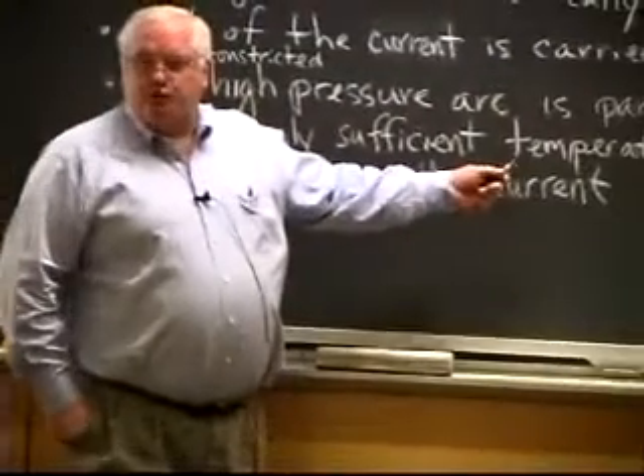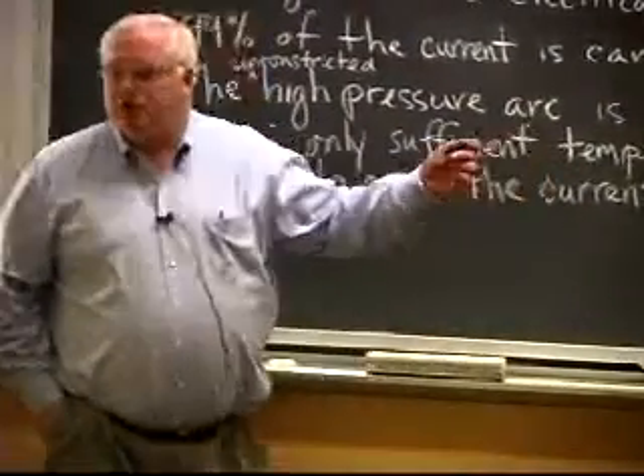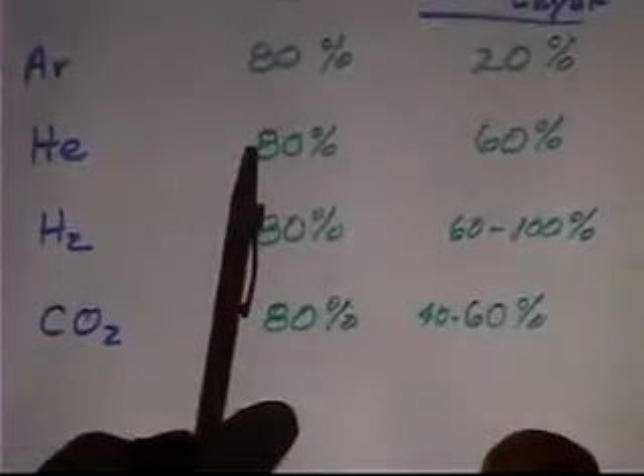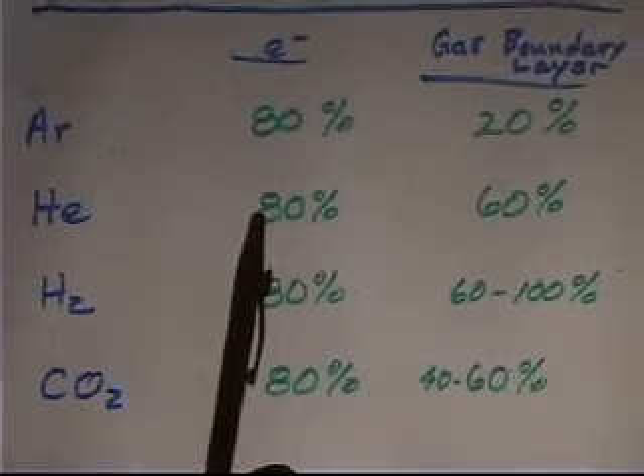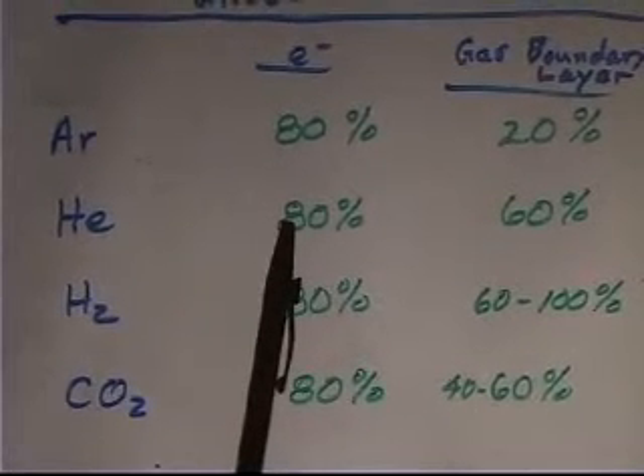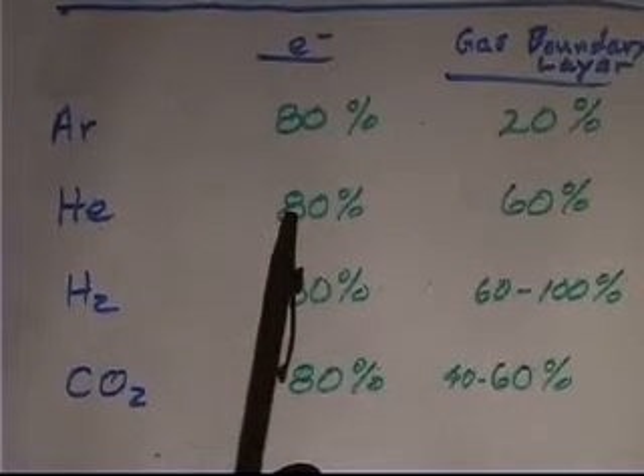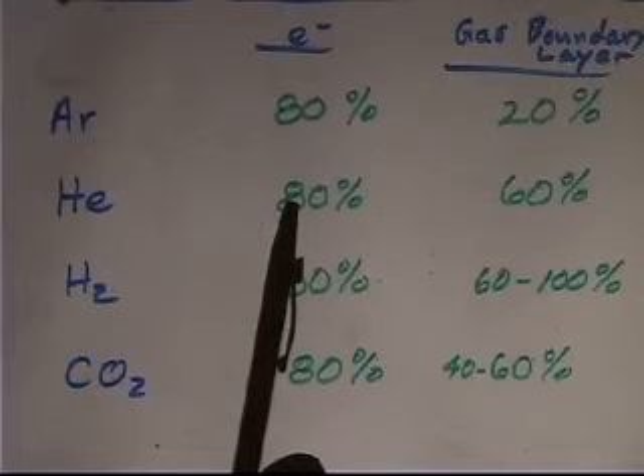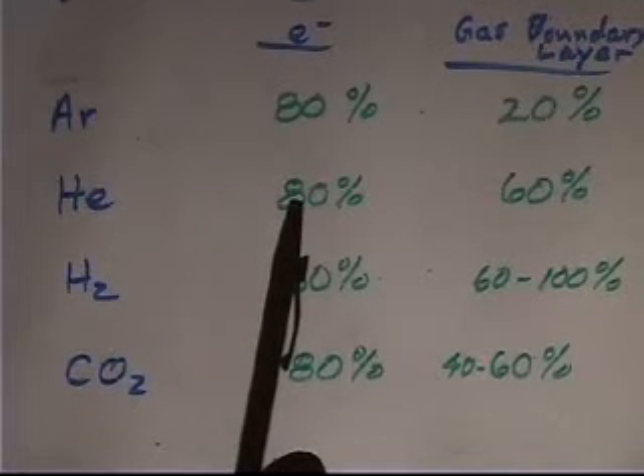Remember what I said at the beginning, the high pressure arc is only going to go to a temperature sufficient to generate enough electrons. And if I have metal vapors there, the metal vapors are easily ionized and they'll produce enough electrons. And so the arc doesn't care whether it's argon or helium from an electrical point of view. The energy carried by the electrons, they could care less. Those argon and helium atoms are just, it's the tortoise and the hare type of thing, where these are the electrons of the fast-moving species. They don't even see these slow-moving ions.